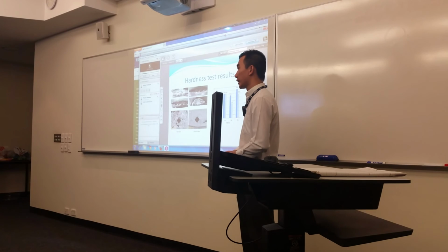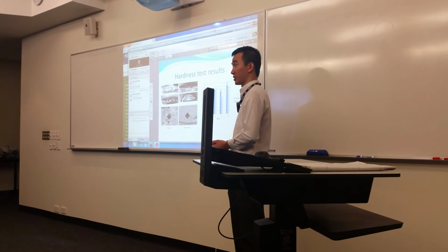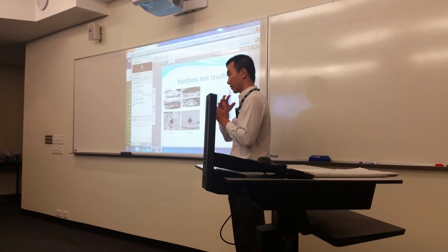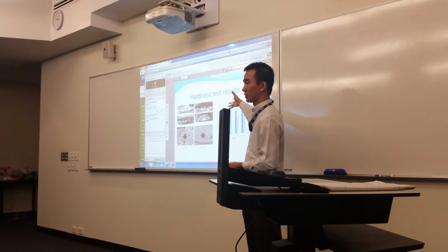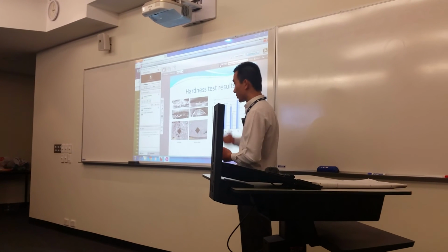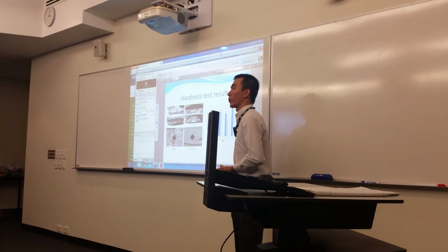austenite will be a more ductile matrix compared to martensite, and usually they have a ductile material in a hard-facing material to take the impact in a wear situation. Of course, a higher hardness means better wear resistance, but high hardness also means the material is more brittle. In an impact situation, it just fractures the whole material if you have too high hardness. Therefore, the ductile matrix will absorb some of that. So it's a compromise between hardness and ductility. I think there is one piece of research that mentioned this in the formation of cavitation inside a pipe, the thermal shock when the bubble collapses. Okay, go ahead.